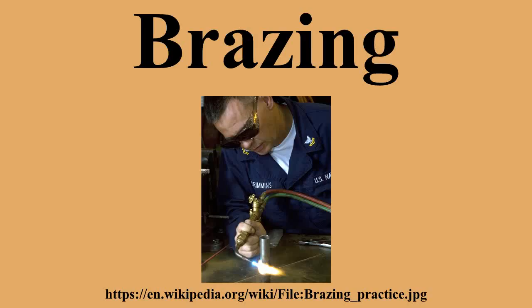Combusted fuel gas: 73 to 75% N2, 10 to 11% CO, 15 to 16% H2. For copper, silver, copper-phosphorus and copper-zinc filler metals. For brazing copper, brass, low nickel alloys, Monel, medium and high carbon steels.